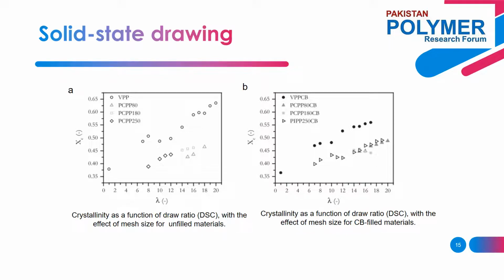function of draw ratio. The crystallinity increases with the increasing draw ratio, and the crystallinity of recycled material is lower than the virgin isotactic polypropylene. Focusing on the differences between recycled material, it is seen that melt filtration size doesn't affect the crystallinity. Filter separate solid particles such as PET of size much greater than the lamellar thickness. Therefore, the crystal formation is not hindered. Overall, this study presented the potential of solid-state drawing process, which significantly enhances the properties of recycled isotactic polypropylene.